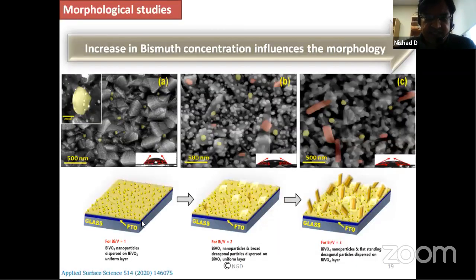Here, the morphology, you can see the nanoparticles we formed had polyhedra-like structures, but when we change the concentration, we see that the nucleation started, and this nucleation is favoring the 020 facets. So you can see most of the polyhedra structures as well as the facets which were shown earlier. And when we change the concentration more at a higher end, what we can see is that rod kind of structures are growing now. So the nucleation is slowly making rod kind of structures where the 110 facet is more effective now. So this means a combined structure is achieved where 110 is more active compared to the 020 facet.